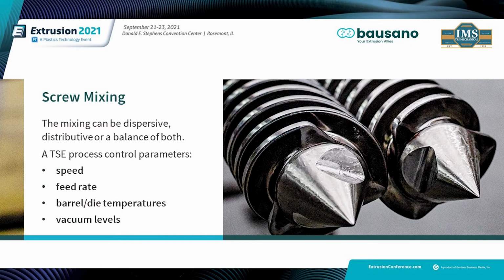Screws are segmented and assembled on high torque shafts, and parameters are adjusted according to process, including additives like calcium carbonate or natural fibers. The mixing can be dispersive, it can be distributive, or it can be a balance of both. The TSE has various process control parameters like speed, feed rate, barrel or die temperatures, and vacuum levels. The TSE can help increase the melt flow index of polymer in a controlled way.